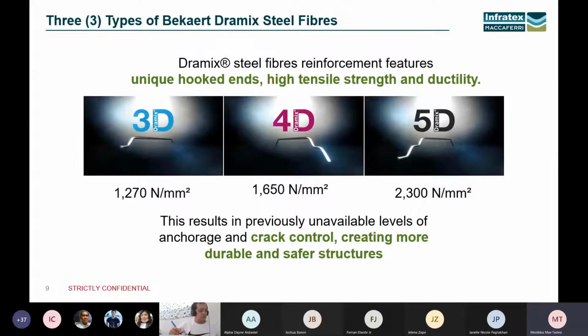Okay, so we actually have three different types of steel fibers that we offer, depending on the strength you need or where it will be used. Dramix steel fibers reinforcement features unique hook ends, so we actually have different hook ends, tensile strength, and ductility. For our 3D fibers, we have 1,270 Newton per square millimeter of tensile strength. For our 4D fibers, we have 1,650 Newton per square millimeter. And for our 5D fibers, we have 2,300 Newton per square millimeter.